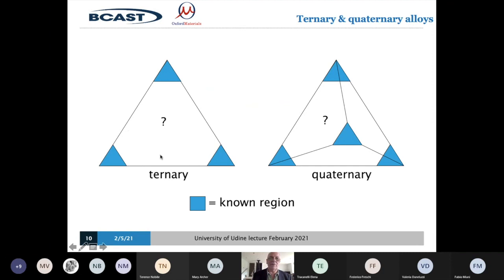So if we want to think about a three-component alloy, three-component material, we depict that on a triangle. And we can think of it as the component A, component B, and component C at the corners of the triangle. It might be nickel here, with adding mixtures of aluminium to give strength and chromium to give corrosion resistance. Well, we add a bit of aluminium, so we move along this. Each point in this triangle represents a different composition. If we add a bit of aluminium, we move along this line. If we add a bit of chromium, we move along this line. If we add a bit of both, we move into this region.